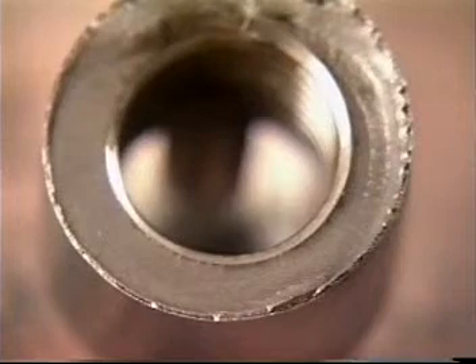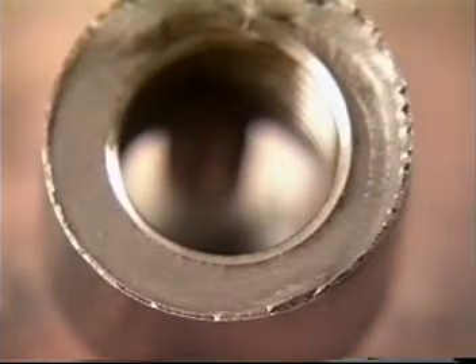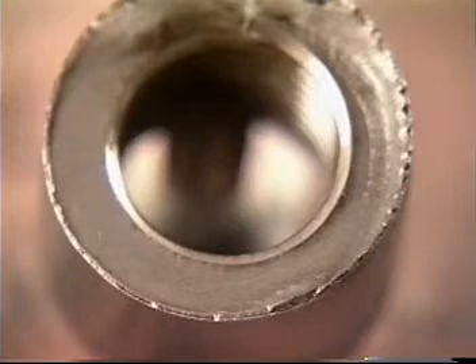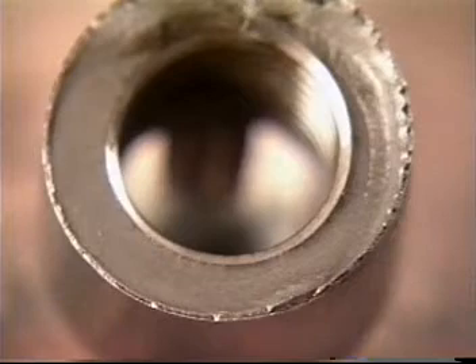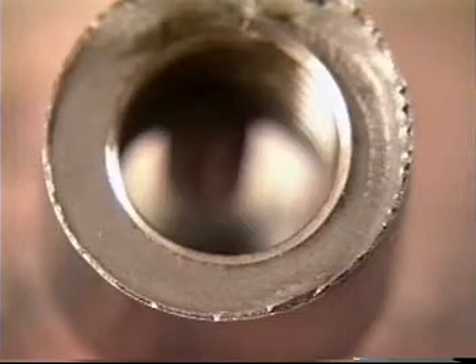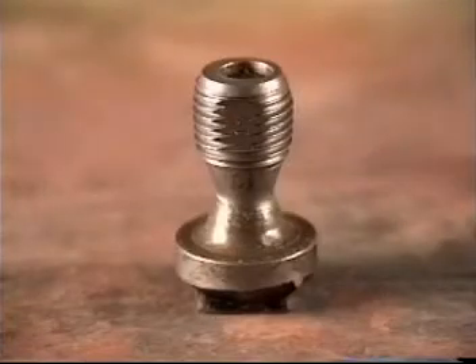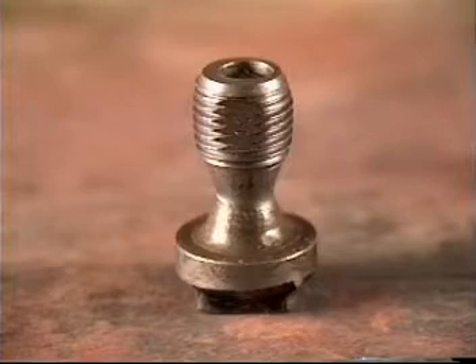Over-torque failures on couplings will show very distinct characteristics. Look for a fatigue failure that completely encircles the face of the coupling, with ratchet marks doing the same. You will also note the ridge that encircles the face. These are the typical signs of over-torque on virtually every class or grade of couplings. Over-torque can also result in pulling the pin completely off the sucker rod on the softer grades of rods.